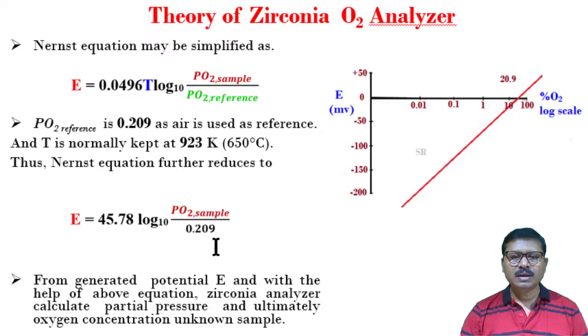Here there are two variables. One is the developed potential and the other one is the partial pressure of oxygen in the sample. So as per the value of the partial pressure of the sample, the value of this potential will vary. So this potential is the indication of the partial pressure of oxygen in the sample, and the partial pressure of oxygen is ultimately the indication of the concentration of oxygen in the sample. Again I am repeating, the developed potential is due to the presence of the sample, and this developed potential is the indication of the partial pressure of oxygen in the sample, and this partial pressure of oxygen is the indication of the concentration of the oxygen in the sample.